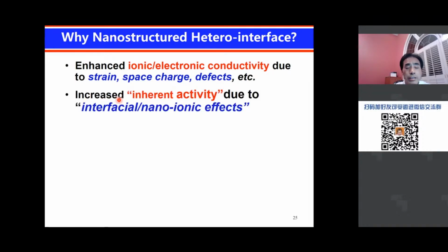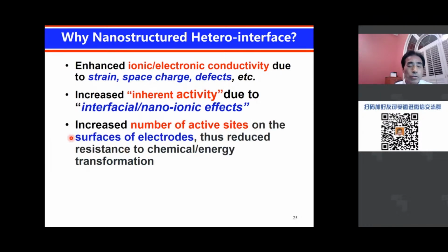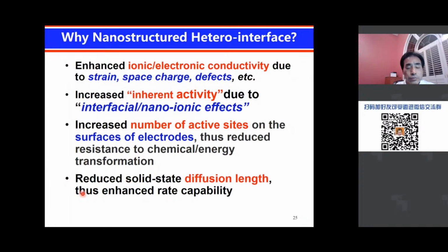Yeah. And it also increases the so-called inherent activity due to the interfacial nano-ionic effect. Now, this has been demonstrated in a few solid ionic systems by creating the interface of different ionic conductors, and that actually can dramatically enhance, for instance, ionic transport. And it also greatly increases the number of active sites on the surface of the electrode, and therefore it will reduce the resistance to chemical energy transformation. So just by simply increasing the surface area, that will also have an important effect. And finally, as you reduce the dimension of the particles, you also reduce the solid-state diffusion length, and therefore that will enhance the rate capability for many of the processes.